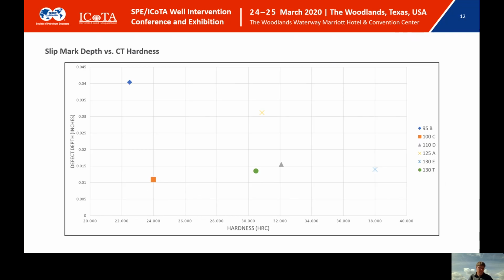So, in this slide we are comparing coil tubing hardness versus the slip mark depth. Again, trying to see if a trend existed. And this is pretty scattered data. It's difficult to say that if you have harder pipe, you're going to have less damage. The reason I say that is if you look at the sample with Rockwell C of 24, it actually had a shallower defect depth than the coil tubing with the hardness of 38. So we didn't see the correlation there that we expected.